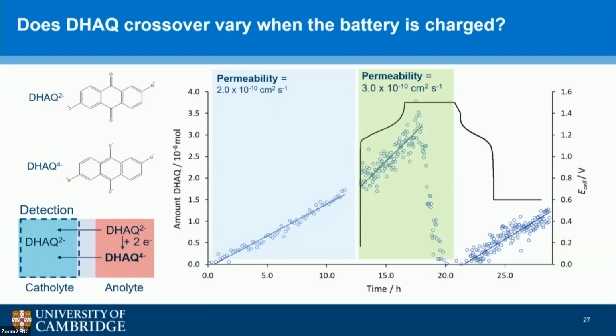Interestingly, this permeability is actually higher than we see when we are not charging the battery, which suggests that possibly migration could actually be driving additional crossover of the quinone here. And then we do also see this sudden drop in quinone signal, which we weren't expecting to see at all. So I've used proton NMR to quantify this, but all of the proton signal is lost. So it shows that the quinone is going to some form that we can no longer detect by NMR, so possibly it's degrading.